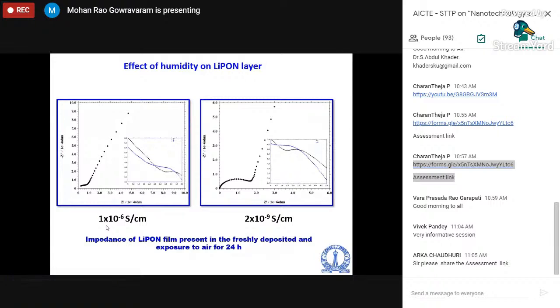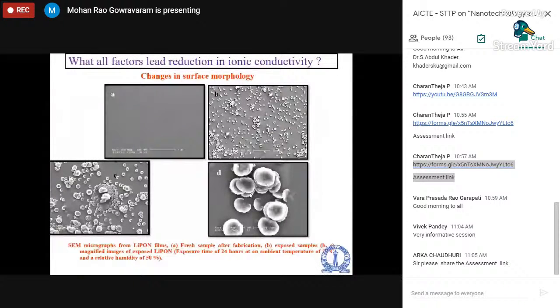Now, having achieved this, you are very happy. You go back, and next day you come back, and again you check its conductivity. And within 24 hours, what you see is an amazing phenomenon: its ionic conductivity reduced drastically. It goes to about 2 × 10⁻⁹ Siemens per centimeter, which means that it will not work. Now you look at the surface of this LiPON film, you see a lot of blisters coming, and you put it under a microscope, then you see that this kind of eruptions have taken place.